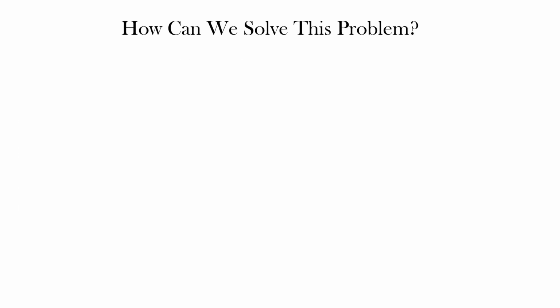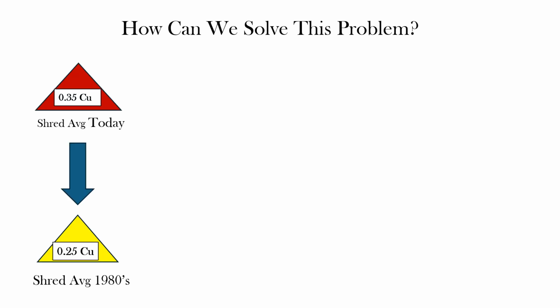Now let's look at how we can solve this problem. What can we do with scrap to optimize its value and help us reduce our carbon footprint? Well, if we simply went back to the chemistry that was available in the 1980s, back from the 0.35 to 0.25, not all the way back to a perfectly clean grade of shredded in today's world, which would be 0.15 copper, but we simply went back 40 years to the chemistry that was available then by controlling the process and knowing the chemistry of what we're putting in our furnaces.